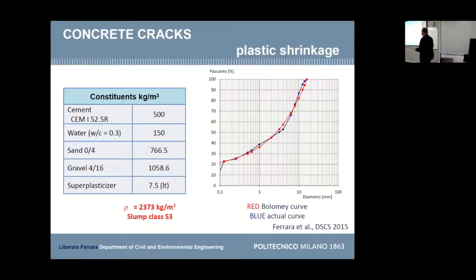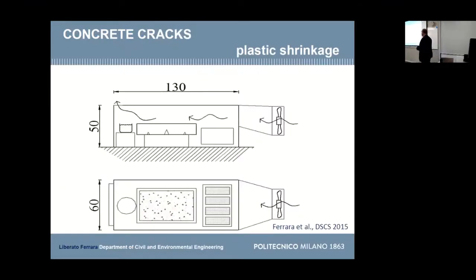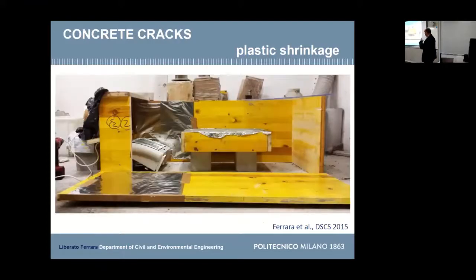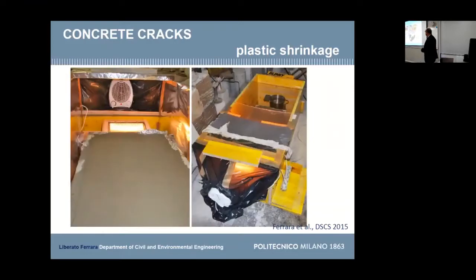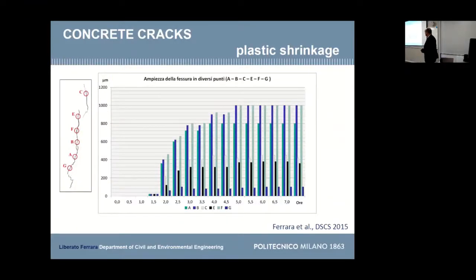And here are some examples of an experiment we did with a homemade setup that we built. It cost us 50 euros going to buy the pieces in the stores. So this was the specimen, this was a heater, this was a fan, and we had here a pot with water on a scale just to check the water evaporation rate, which is the parameter set by the standard. You see this was the setup once opened, some pictures, and you see the cracks. This is the crack width monitored with a portable microscope. The cracks started appearing 1 hour and a half, 2 hours after casting. So you just cast and the crack starts. And well, the setup is made to exacerbate cracking, but we had cracks up to 1 millimeter.